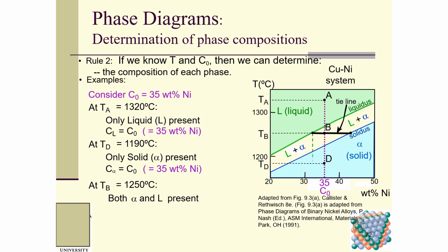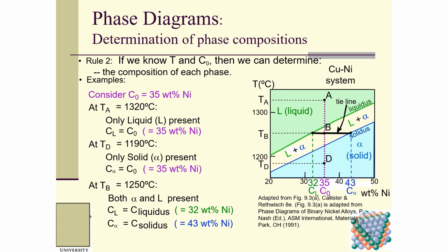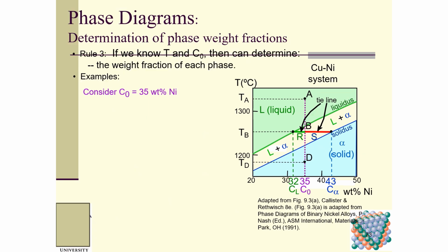And then we draw vertically down from this intersection point and this intersecting point. We know that here CL equals this point, and C alpha equals this, right? So you can get the composition of these two phases based on rule 2. And rule 3: if we know T and C0, then we can determine the weight fraction of each phase.